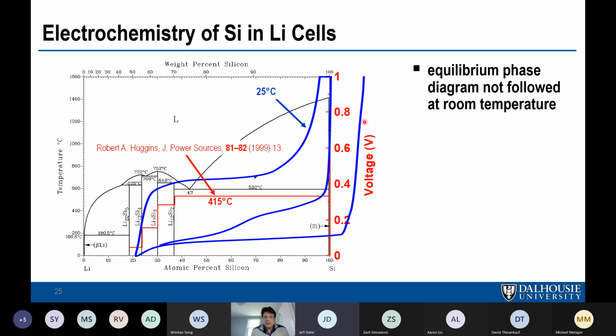Okay. So yeah, when you have everything together, you can get a half decent voltage curve. And this is what you get for silicon. So you lithiate silicon, you get something that looks like a plateau, a two-phase region, which the phase diagram has here. And then you don't see any of these phases, kind of like tin, high melting point and big unit cells. And then when you delithiate, you see another two-phase region.